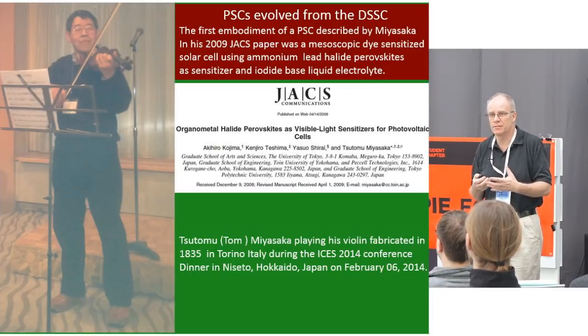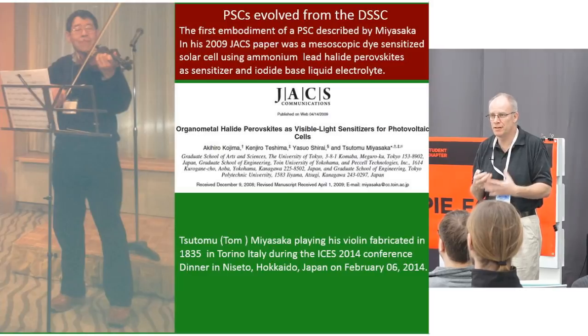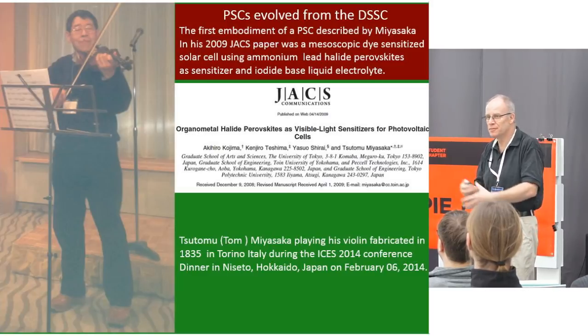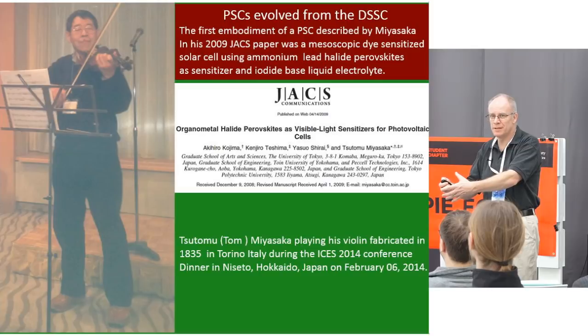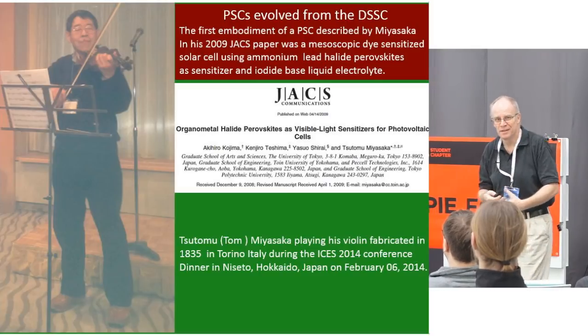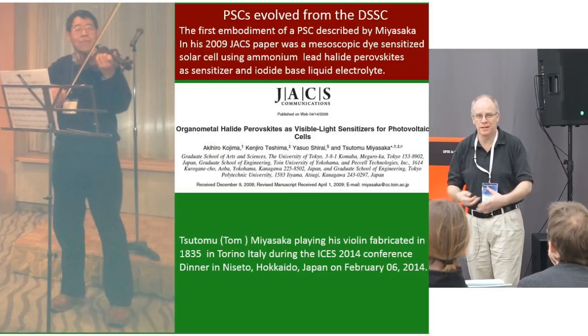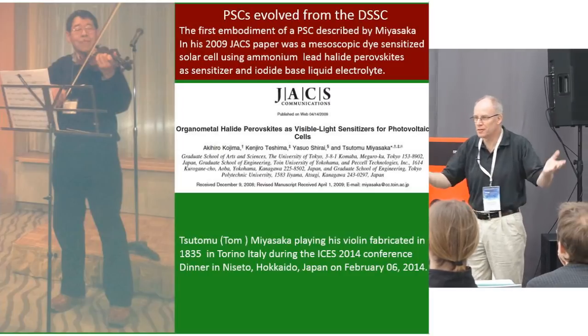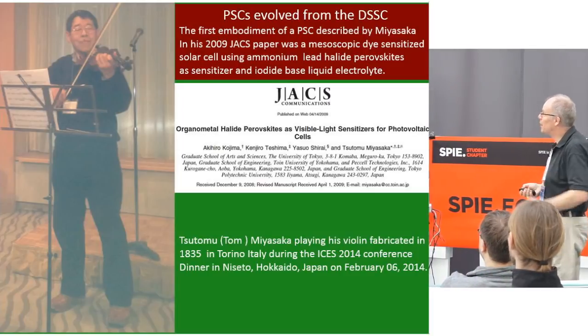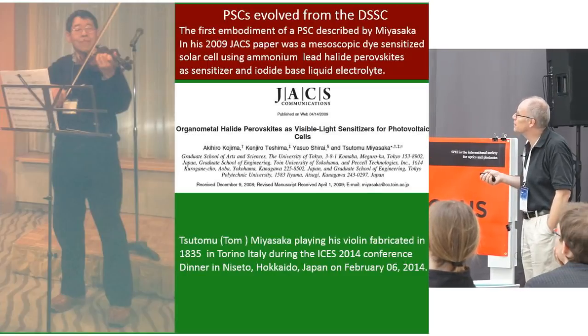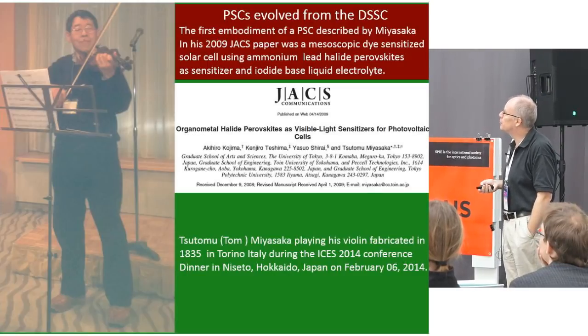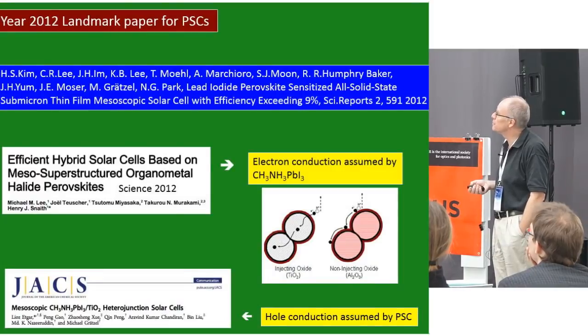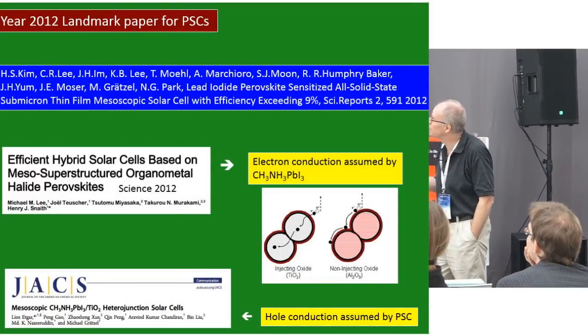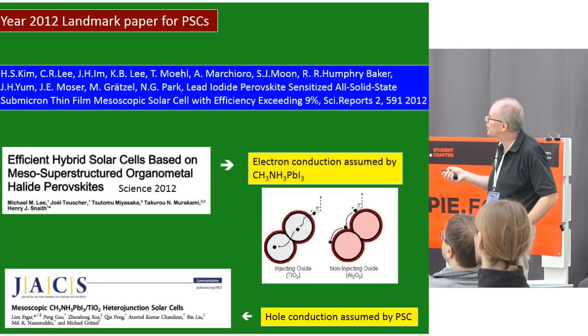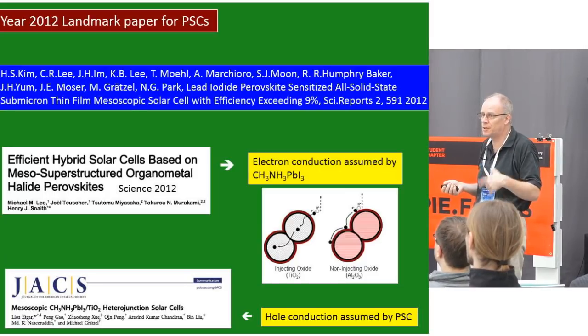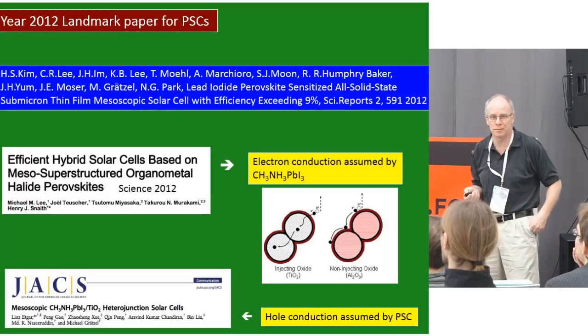And he also said that, well, to measure it, I have to be very fast. I have to run from the lab to the solar simulator because stability is maximum 10 minutes. Then the perovskite dissolves into the iodide electrolyte. So it's gone in 10 minutes. He published that 2009, and not very much attention was paid to it. But 2 things happened. One was that Nam-Gyu Park in Korea, he had worked with perovskite in his PhD for other reasons, but he felt perovskite I know about. I will try to repeat what Miyasaka is doing.